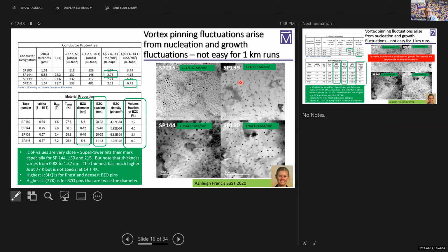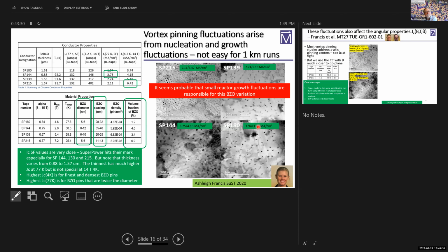So here are some pictures. I won't go into the details of this, but these are all made to the same specification. What we're looking at here are columns of nano barium zirconate, and they're all to the same magnification. So you can see here the density is lower, the size is bigger, here the density is lower, here the density is highest, here it's even lower. And so this is at low temperatures 6 megaamps per square centimeter. This is 3.7 megaamps per square centimeter. So we have something which is not reproducible.